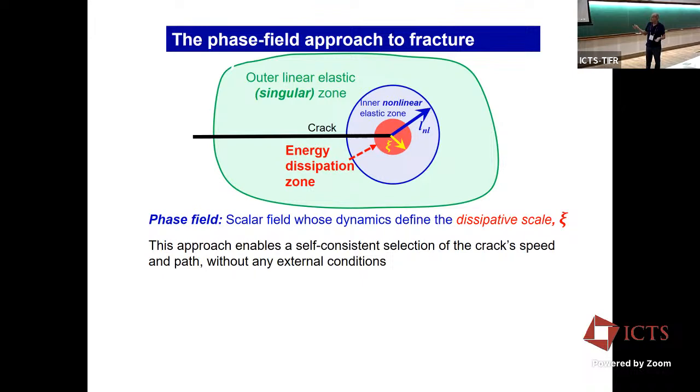And basically, the scalar field defines the dissipative scale, okay? So you have linear elasticity, and then you can also add nonlinear elasticity in this region, and xi here is the dissipative scale. So these are the simulations, and this approach enabled one to self-consistently calculate what the crack is doing.